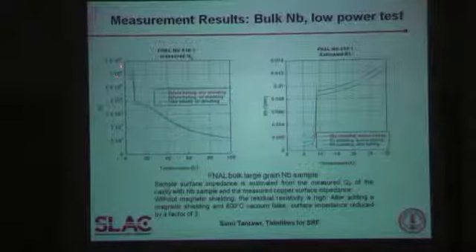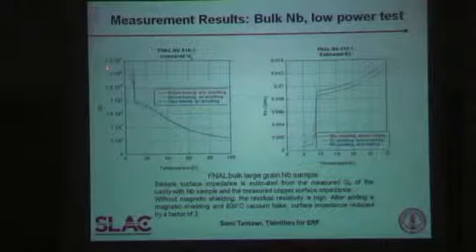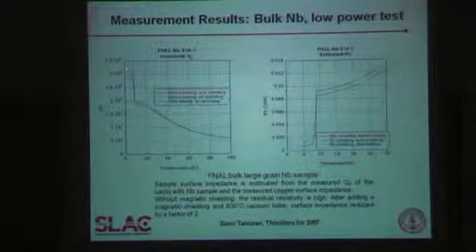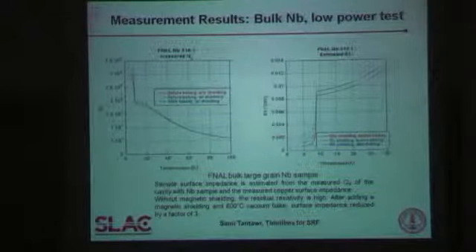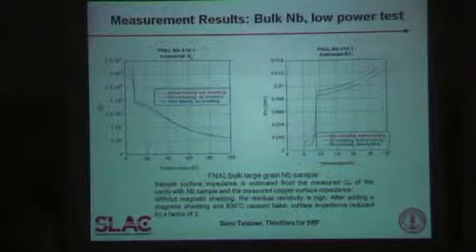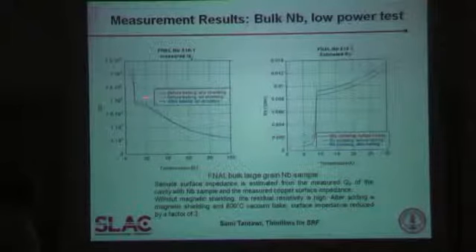As mentioned, if the sample has zero resistivity, the quality factor at the sample surface reaches about 3.5×10⁵. After we started adding magnetic shielding the resistance began to improve. We also learned that if the niobium sample has been exposed to air for a long time, it must be baked to drive out gases. The calculated residual resistance based on quality factor measurements was still rather large — although we were working at 11 gigahertz, we didn't expect it to be that high.